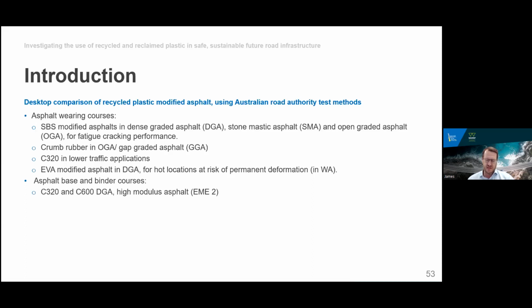where they, or what mixes they're presently using, for example, in terms of wearing courses on highways and freeways, or what they're doing in terms of asphalt base courses. So just to put Western Australia and Queensland into context, typically in their asphalt wearing courses, they would be using SBS modified asphalts in dense graded asphalt and in stone mastic asphalt and open graded asphalt mixes. And one of the main reasons for this, especially for the dense graded and the stone mastic asphalt, is to get improved fatigue cracking performance. So when I say SBS modified asphalts, I'm considering A10E, A15E type binders.